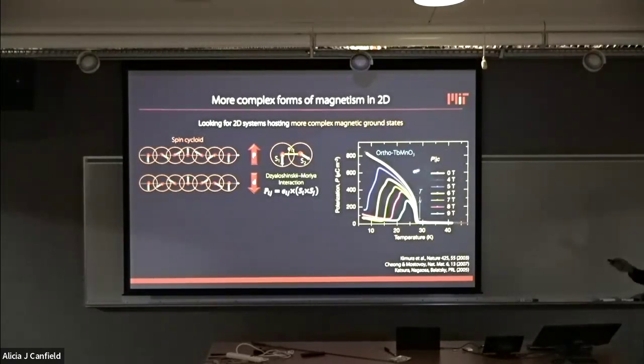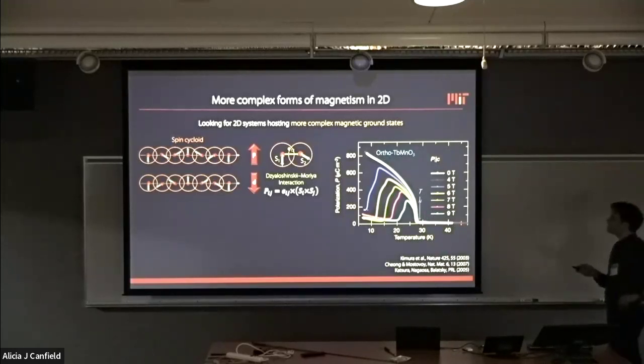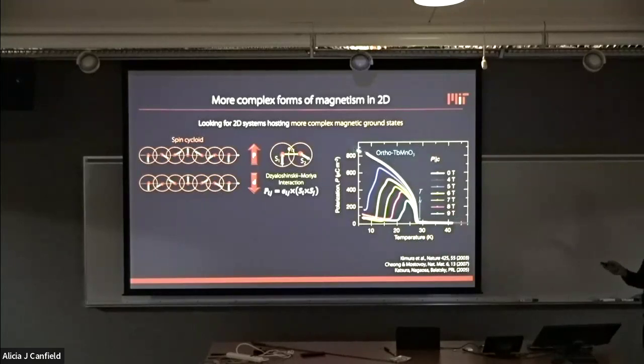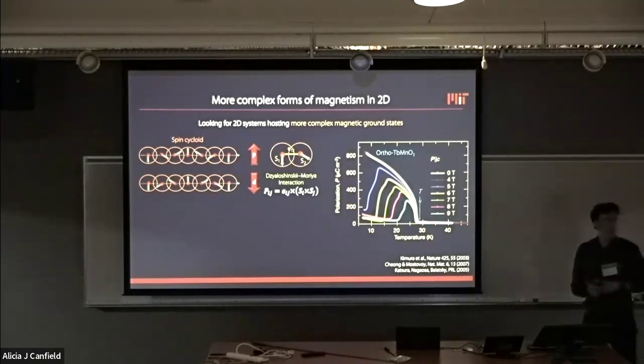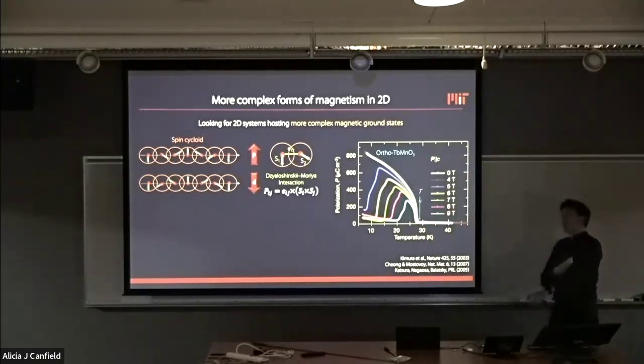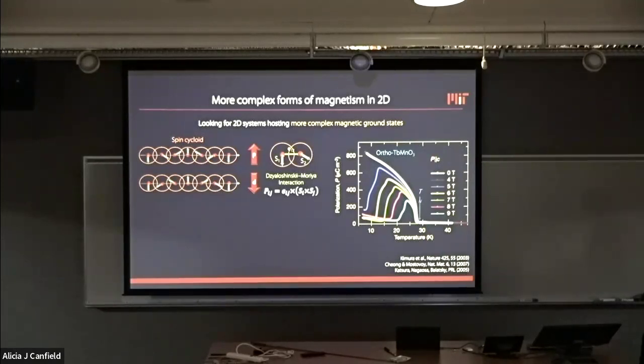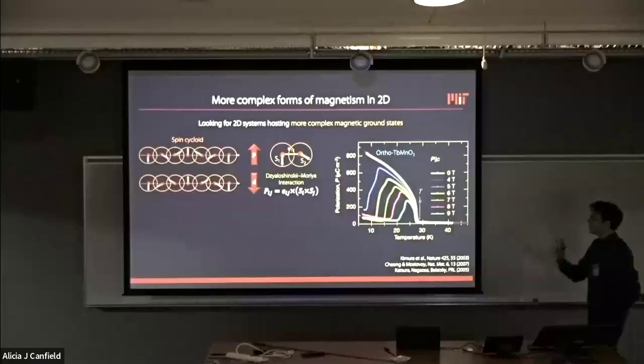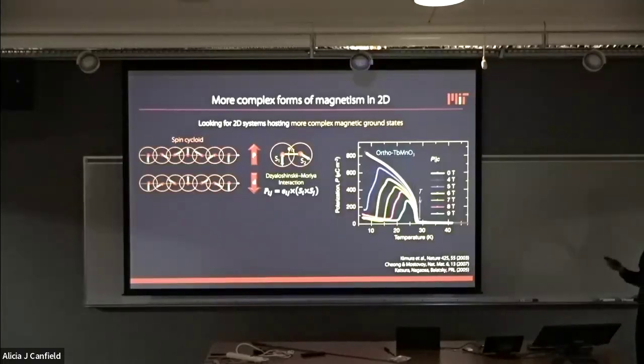And this discovery was made more than 20 years ago in the Kimura group, in the material terbium manganite. What you see here is the polarization measured as a pyroelectric current that onsets at the Néel temperature of this material, and then it can be tuned with a magnetic field. That's a direct demonstration of magnetoelectric coupling. That's what got a lot of people excited back in the day about the realization of type 2 multiferroics. It's this very direct coupling between the charge and the spin degrees of freedom, so the possibility of controlling magnetism with electric fields and vice versa, controlling ferroelectricity with magnetic fields.